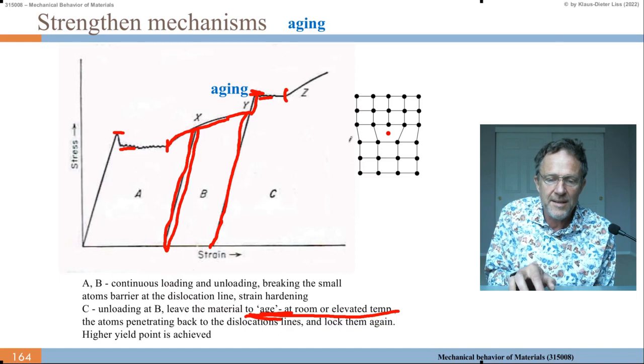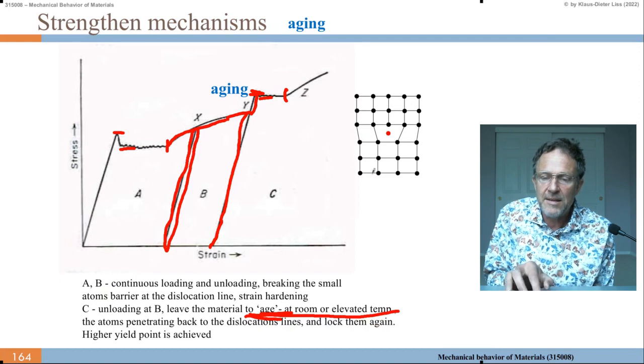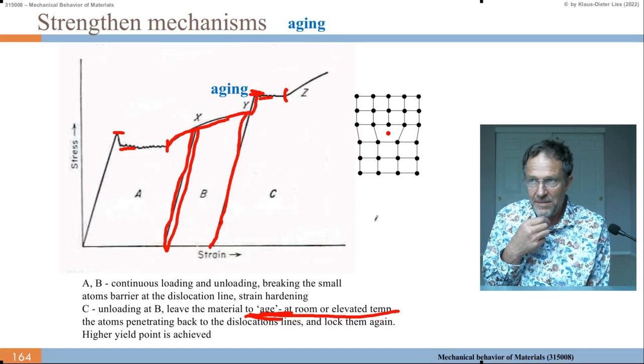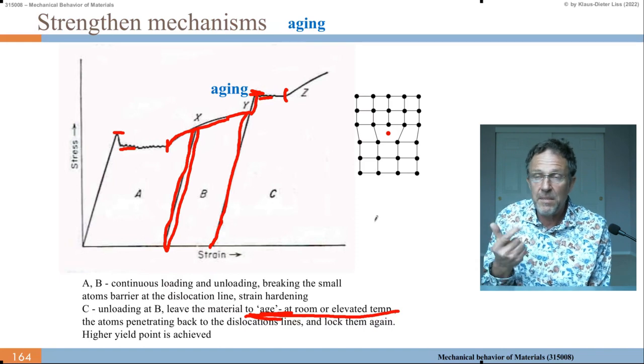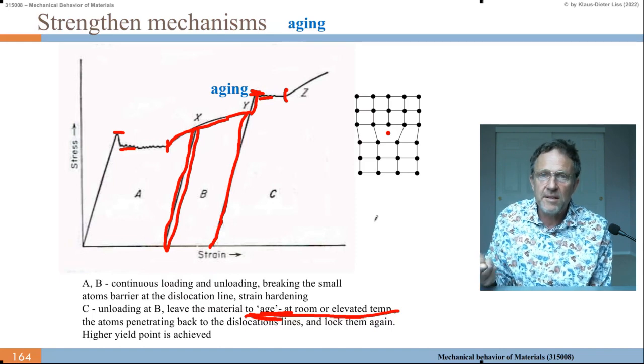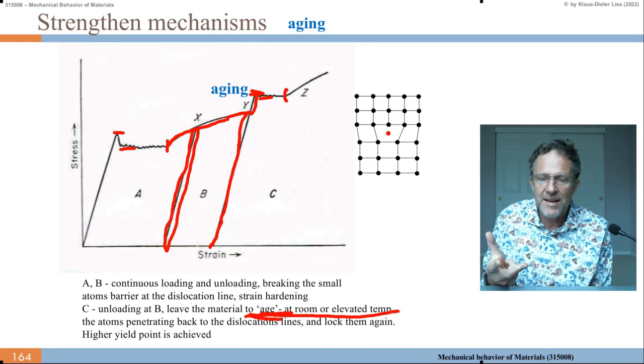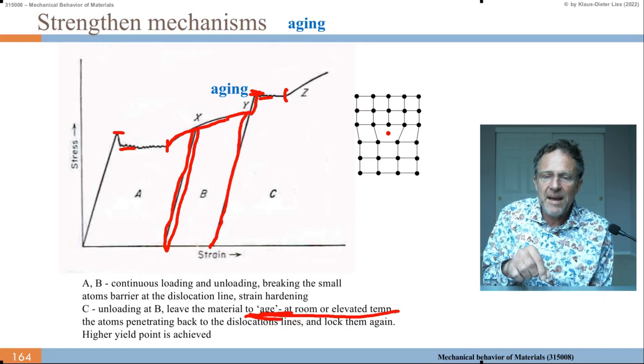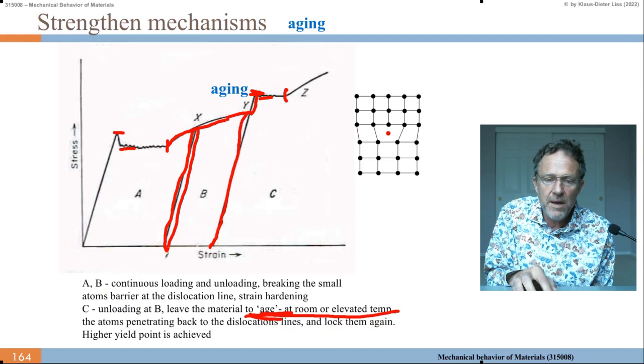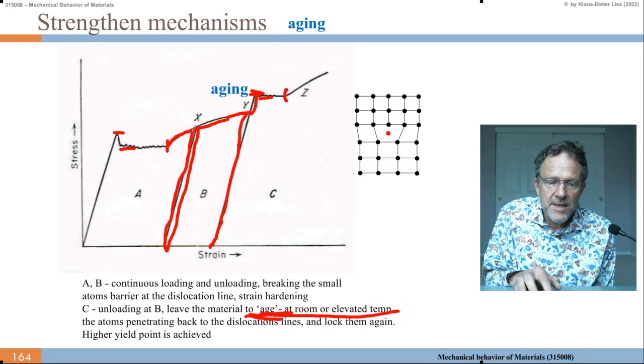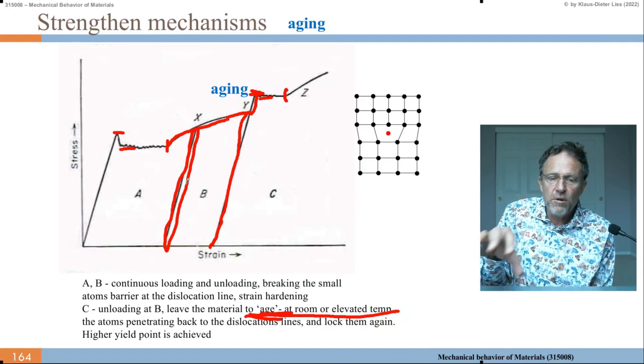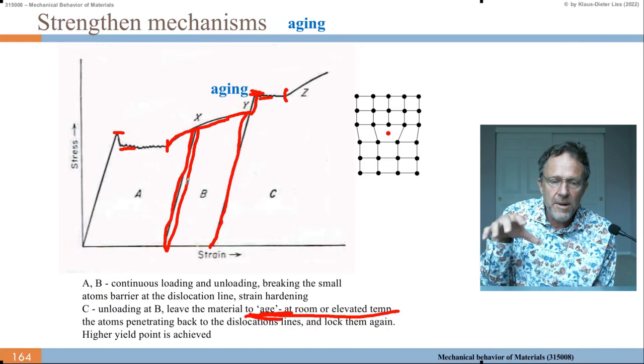So what happened in the aging? In the aging, we have diffusion of the carbon atoms within the crystal lattice, and so time, diffusion time, and maybe temperature. Carbon goes interstitial, so it goes relatively fast. So the carbon moves back to the dislocation. Here, if you do nothing, immediately unloading and loading, there is no time for segregation of carbon to diffuse. There's no diffusion time to go to the dislocation.